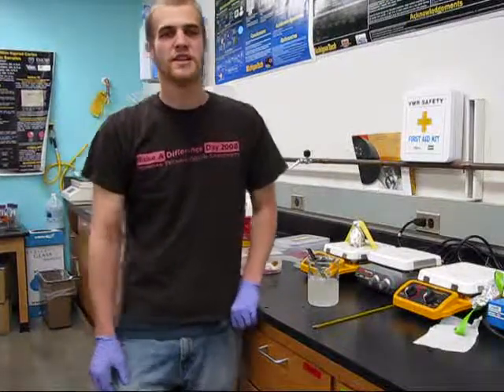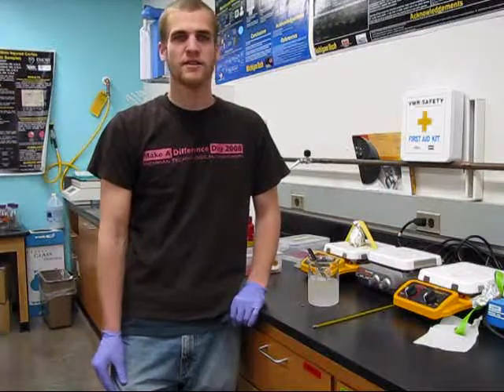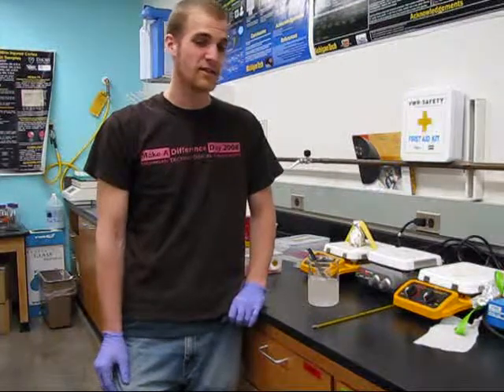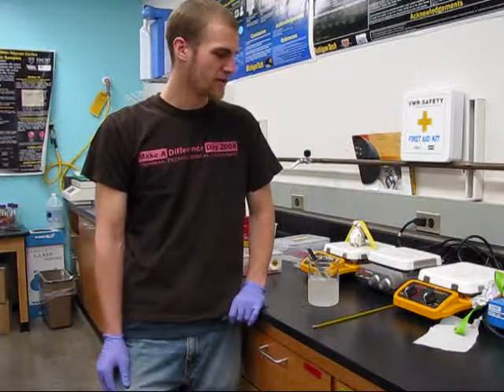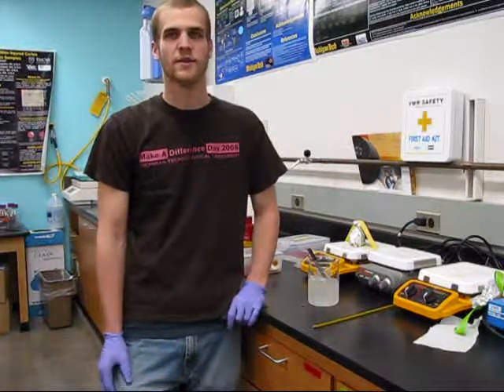My research currently is adding dextran to our hydrogel, because it's much different than the spinal cord, and it also takes a long time to form a gel — about 10 minutes. So we're trying to get that time down to around 2 minutes, and trying to make it much softer so that neurites can grow through the gel and repair the spinal cord.